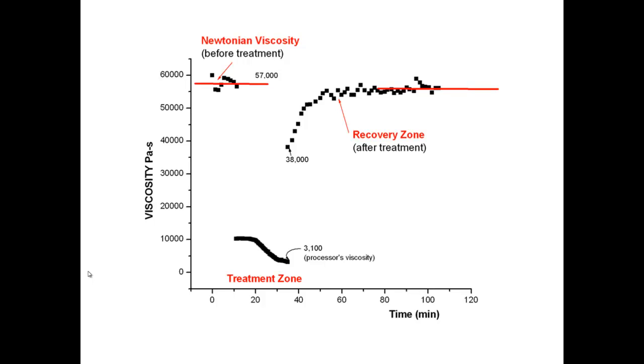It will just springingly go back to the same value it had. Here, because there was this coupling with strain softening, and especially time-dependent strain softening, you see that the recovery occurs in 2 steps. One fast one, and then a slow recovery, which is taking time, and which we'll study here, and which we question the origin of this phenomenon. Okay, so the real fluidification is observed here, and we are going to understand, or try to understand, this phenomenon,